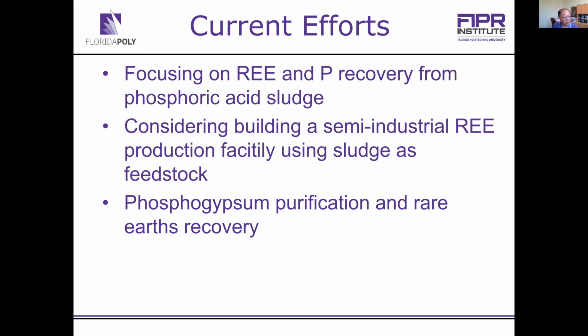Phosphogypsum is tricky because currently it's regulated by EPA because of a low level of radioactivity. So phosphogypsum has to be stacked. After it's pumped to the stack, you cannot touch it anymore. So in order to recover rare earth elements under the current environmental regulation, we have to reduce the radioactivity level down to 10 picocuries per gram. That's a radioactivity level. So we are doing that type of research, trying to first reduce the radioactivity, then recover the rare earth elements from phosphogypsum, because the sheer volume of the phosphogypsum makes it a very viable source of rare earth, but we have to get the radioactivity reduced first.